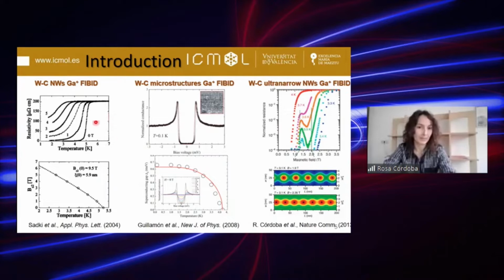Okay. So let me mention that Sadki and co-workers reported in 2004 that these tungsten carbon nanowires, grown by using a gallium focused ion beam, behave as superconductors below 5 Kelvin, and the applied magnetic field was around 9.5 Tesla. So the magnetic field can penetrate into this material, creating vortices. And I would like to mention two works already done by our group in the last decade using different characterization techniques, scanning tunneling microscopy and spectroscopy. From those results, we can say that this material properly follows the microscopic BCS theory.